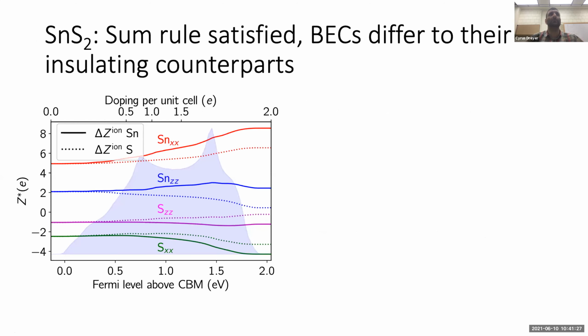So these are the results for tin sulfide. I'm plotting the Born effective charge versus Fermi level. In the background, you can see the density of states of this single conduction band. Since the material is anisotropic, we plot the Born effective charges on the tin and sulfur sublattices for both the in-plane X and out-of-plane Z directions. The solid lines are if we attribute the extra positive charge, compensating the electrons that we add, to the tin sublattice, and the dotted lines are for the sulfur sublattice.